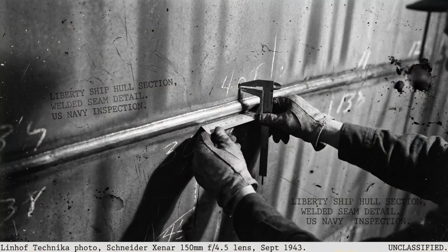This ductile to brittle transition temperature varied depending on the specific composition of the steel, but for many Liberty ships, it was disturbingly high, sometimes above freezing. In the frigid waters of the North Atlantic, the hulls were operating below their safe temperature range. The problems were compounded by stress concentrations in the original design.